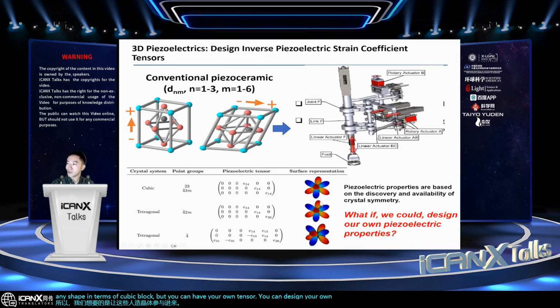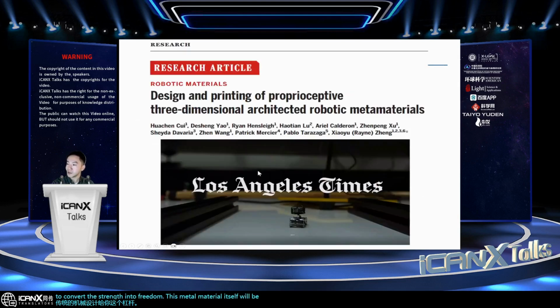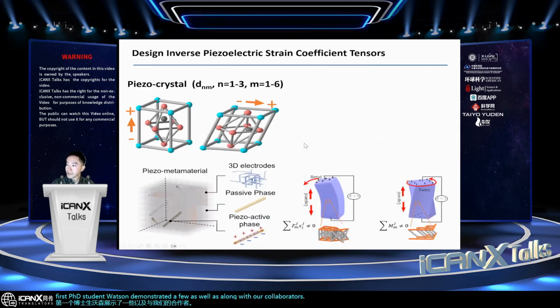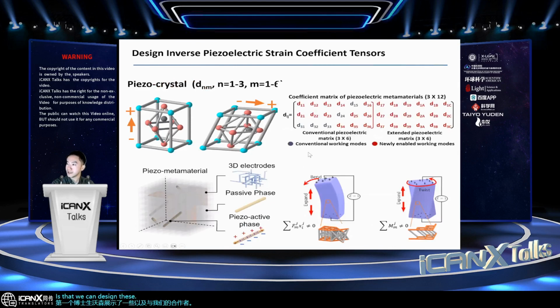You can design your own tensor in such a way that you don't have to use complex traditional mechanical designs with levers to convert the strain in different degrees of freedom. This metamaterial itself will be capable of generating strain in different directions. This is from work that my first PhD student, Huachen, demonstrated along with our collaborators. We can design these metamaterial topologies by arranging the orientation of the piezoactive materials, as well as the passive structural phase, which can be a ceramic phase that is non-polarized, and conductive phases.